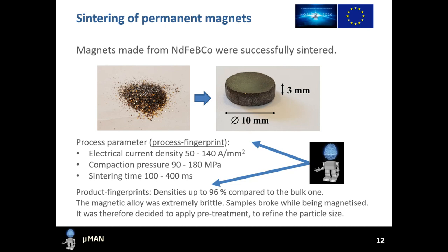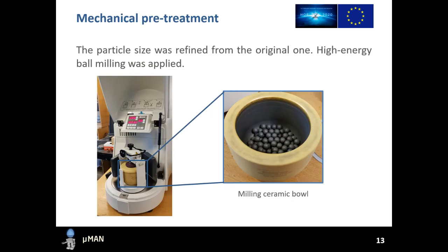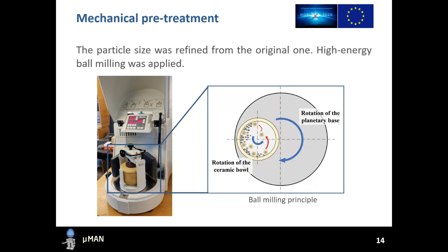Process parameter ranges were similar to the titanium case. Due to the high brittleness, the original powder was pre-treated to be refined and therefore increased the mechanical strength. To do this, high-energy ball milling was applied. A ceramic bowl filled with 100 spheres was rotated at high rotational speed. The impact of the spheres with the powders provoked the refining of the particle size.